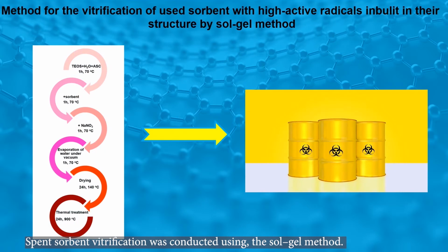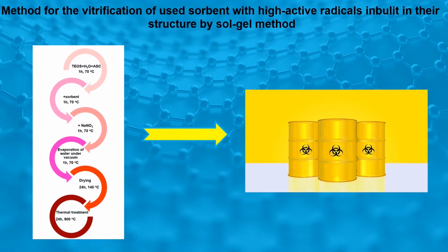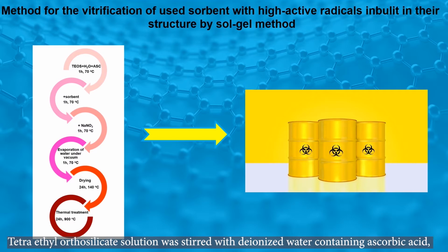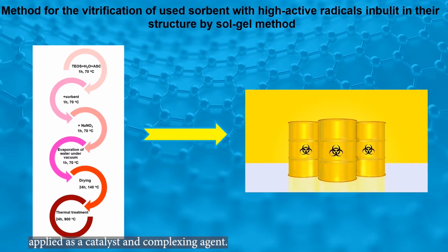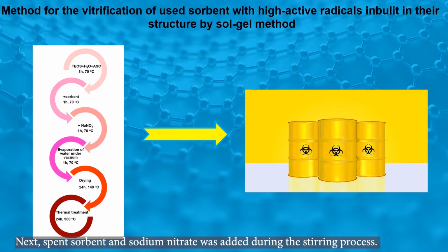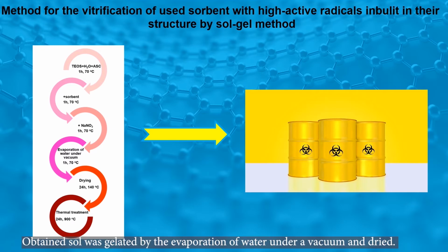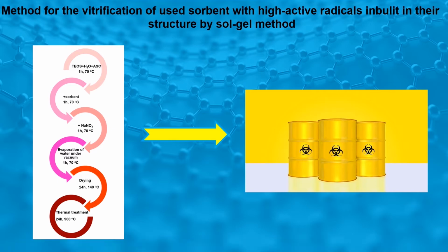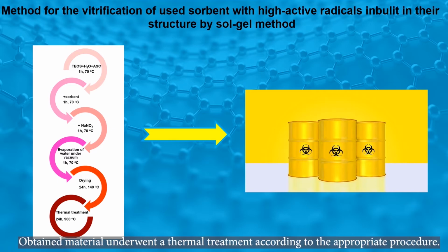The spent sorbent vitrification was conducted using the sol-gel method. Tetraethyl orthosilicate solution was stirred with deionized water containing ascorbic acid, applied as a catalyst and complexing agent. Next, spent sorbent and sodium nitrate were added during the stirring process. The obtained sol was gelated by the evaporation of water under a vacuum and dried. The obtained materials underwent a thermal treatment according to the appropriate procedure.